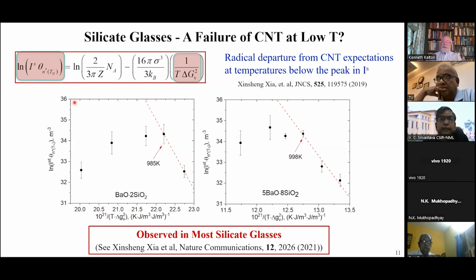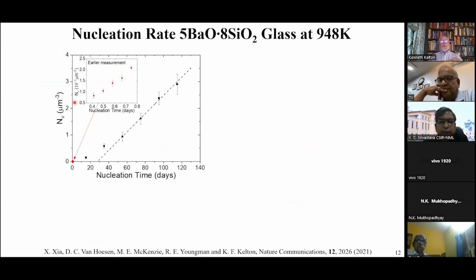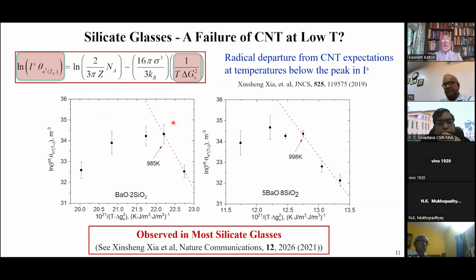And so, again, if you go to the literature, up until about 2 years ago, you could find many, many theoretical explanations for why the classical theory was failing. But it turns out it's more complicated. Here are the data measured at the lowest temperature in that previous study that I showed you for these silicate glasses.